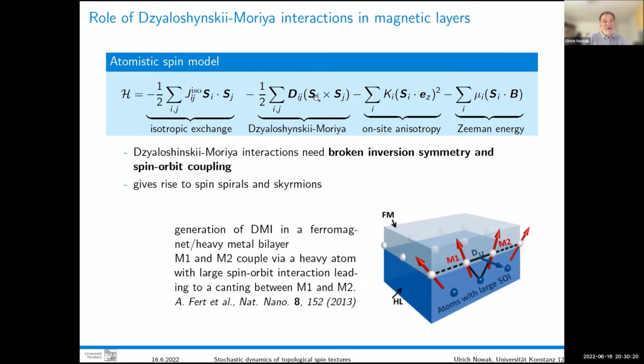And this cross product means that the spin structure will somehow be twisted. So it will not be just ferromagnetic, but somehow twisted. The ground state could now be, depending on the details of this interaction, a spin spiral or so. And in connection with anisotropy and field, it can be a skyrmion. So this twisted structure comes from the Dzyaloshinskii-Moriya interaction in that case.